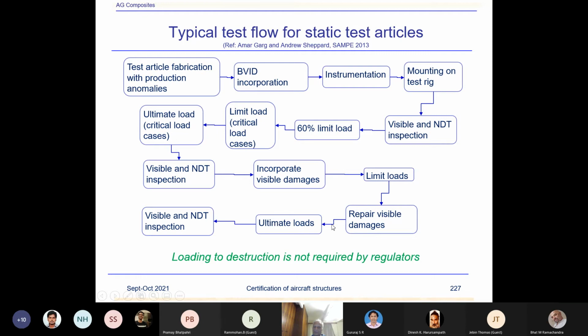Now, one would ask, why don't we load it to failure? Failure is not a requirement for FAA. And generally, we don't try to load it to failure. There's no use. It may go to 120%, 150%. But what we are trying to show by analysis, once it has shown by analysis that the strains and LVDTs are working well, then I'll show in the next slide the compliance procedure.